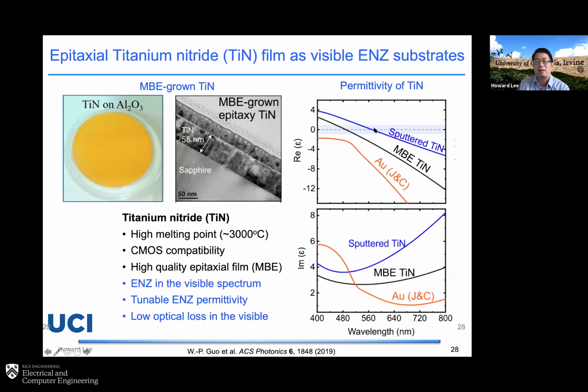So basically, you can control the ENZ wavelength in the visible range, where most of the emitters emit. That's why you can make use of this ENZ effect here. And at the same time, they are relatively low loss as well. If you look at the MBE titanium nitride compared with a metal like gold, it has a much lower loss in the visible range below, for example, 540 nanometer. And that's why you can use it as a low loss metallic material as well.